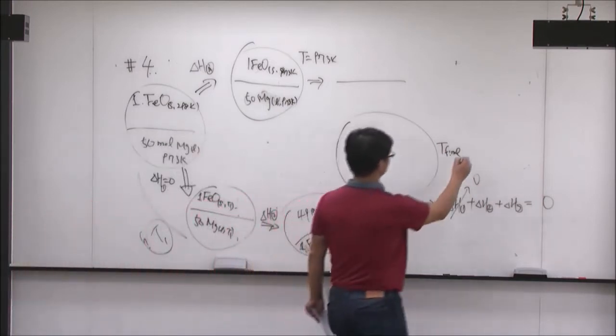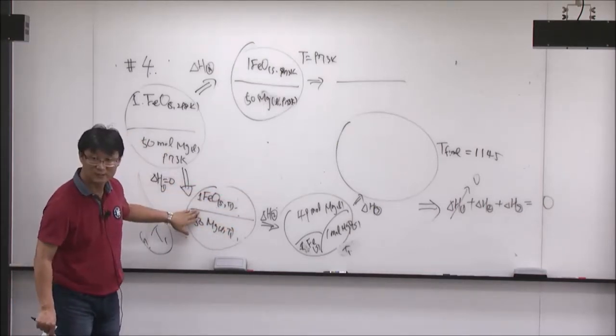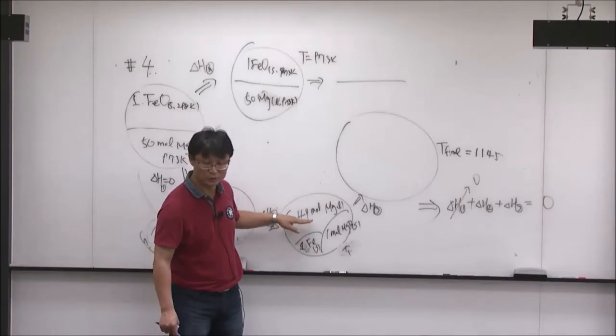Some of you did the chemical reaction step correctly but then only took 49 moles of liquid magnesium to the final temperature — without including MgO and Fe in the heating step. That's obviously wrong. You have to take MgO and Fe along to the final temperature as well. The answer would be slightly different, but the calculation method was completely wrong, so I took out the marks. There are various intermediate temperature approaches possible — 973 K or even 298 K — all eventually give the same result as long as you account for all species.